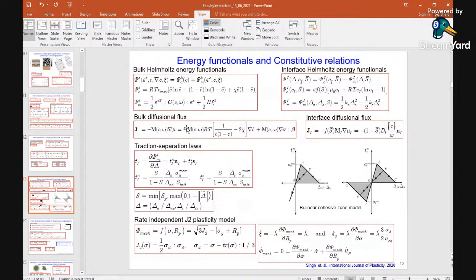In the diffusion flux, we have two components: one is the chemical part and one is the mechanical part. The mechanical part is related to the gradient of the stress. The stress gradient will build another diffusion flux, which is one of the important aspects of this chemomechanical process. In the chemical part, we have also taken both components, the entropic part and the enthalpic part of this exchange process, because the diffusion of the lithium is not like a dilute solution. It interacts with the host atom.